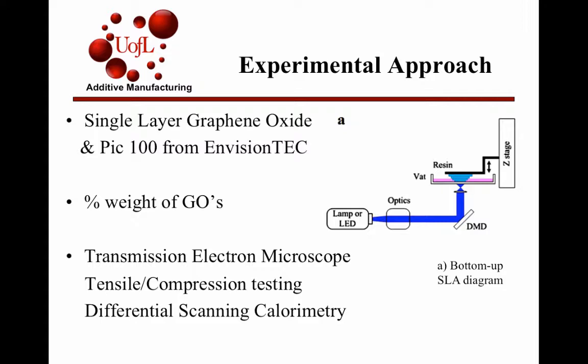The factor that they changed in this experiment was the percent weight of the graphene oxide, to experiment with how much graphene oxide affected the tensile properties, the strength properties. The way they measured that, they did some transmission electron microscopy to look at the actual structure and how the single layer graphene oxide looked inside the polymer. They also did some tensile and compression testing and some differential scanning calorimetry, which has a lot to do with the melt and crystallization properties of the polymer.